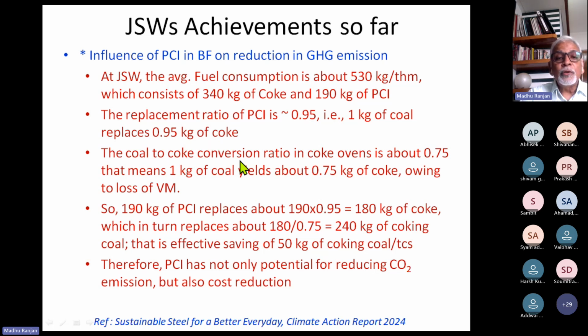The coal to coke conversion, when we take coking coal and make coke, the conversion ratio is 0.75. The rest 25% goes into the atmosphere. They are volatile matters. That means 1 kg of coal yields about 0.75 kg of coke owing to loss of VM. They are not lost, they are used elsewhere, but here the yield is 0.75 kg only.